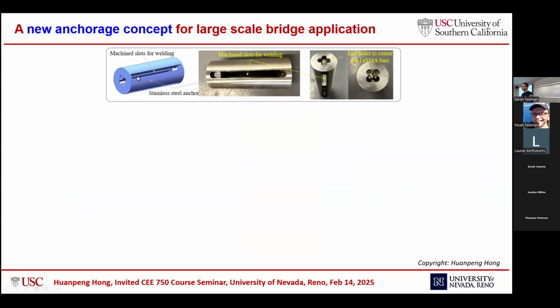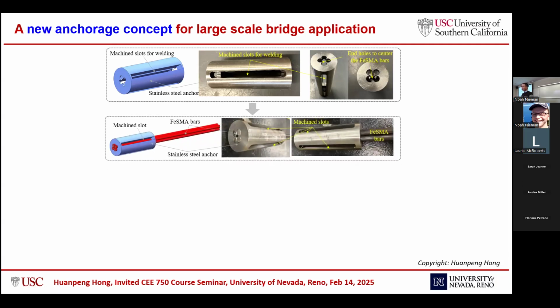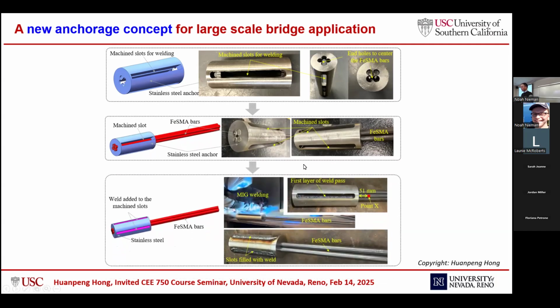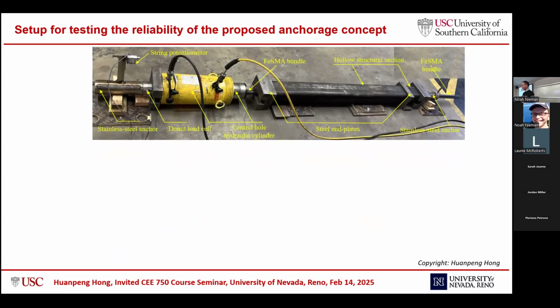It is still a stainless steel anchor. We see there's a petal pattern here. For large-scale applications, we need not only one bar, maybe 4 bars, 6 bars, maybe 10 bars. Using this concept, we can add as many bars as we want. The second step is we pass the iron SMA bars through the middle, and then apply the welding in the welding slots, and then these bars are anchored to the stainless steel anchor.